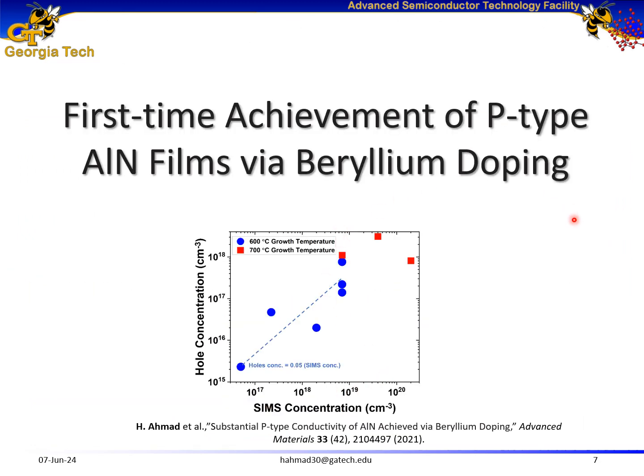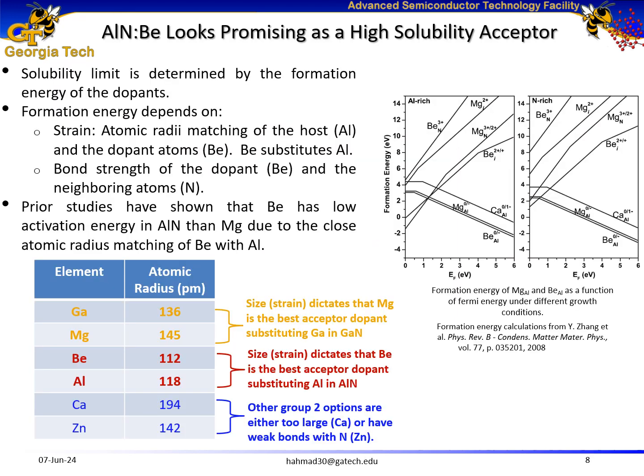So I performed a study on first time achievement of p-type aluminum nitride films via beryllium doping. The solubility limit of a dopant is determined by the formation energy of the dopant. Formation energy further depends on the atomic radii matching and the bond strength of the host versus dopant atoms. We know that in case of gallium nitride, magnesium closely matches in terms of atomic radius with the radius of gallium in gallium nitride, so it is found to be the best p-type dopant in gallium nitride. By similar hypothesis, beryllium closely matches with the atomic radius of aluminum in aluminum nitride and is potentially the best candidate as a p-type dopant in aluminum nitride.